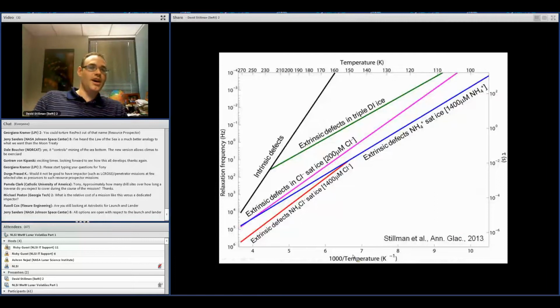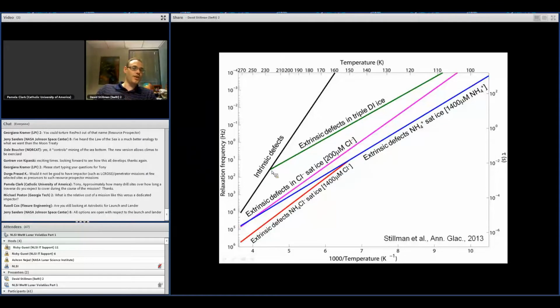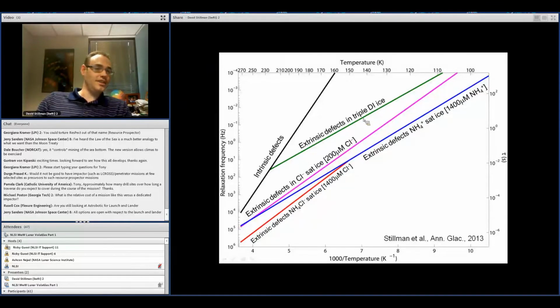So this is this plot here. We've got 1,000 over T on the bottom. I show temperature in K up here on the top. We've got relaxation frequency decreasing as we go up on this left Y scale. For that Lake Vostok ice, it will follow this black line, which is the intrinsic defect. Every ice crystal out there has intrinsic defects in it. Then it will start bending over and following this green curve. This green curve is when we actually have extrinsic defects in there, either chloride substituting in for the H2O in the crystal lattice, fluoride, ammonium, things like that. Even in our triply deionized samples on Earth, we always get this bare minimum of extrinsic defects, and this Vostok sample also follows this. And this is measured all the way down to these temperatures, showing where this ice relaxation is.